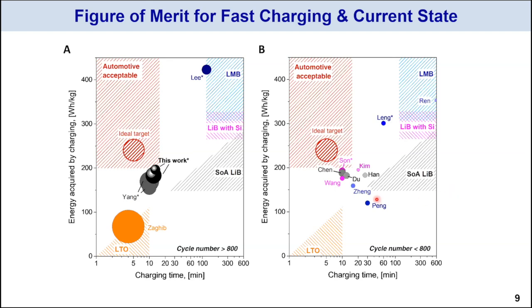Now, this figure of merit consists of three metric parameters: charge time on the horizontal axis, obviously, right? And then the vertical axis is energy acquired by such fast charging in watt hour per kg. And one can also use areal capacity acquired by fast charging in milliamp hour per kg. It's the same thing. And that is important because you need sufficient energy for automotive driving. And then the third parameter is basically the number of fast charge cycles. And that is a measure of life and represented by the size of the bubble on that plot.